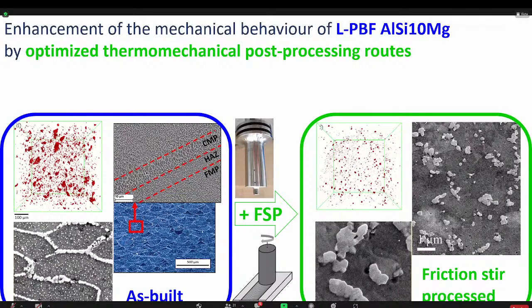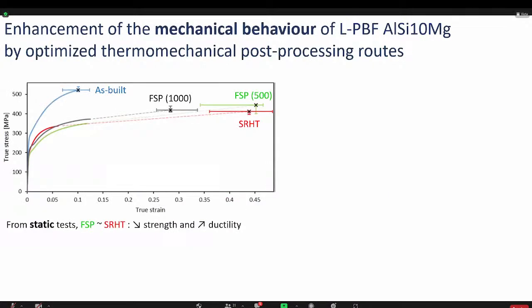In terms of mechanical properties, here you can see the static mechanical properties. If you compare, the FSP material is the green one, and the as-built is the blue one. We also compare it with some stress relief material for the red curves. You can see that the FSP material and the stress relief material have quite similar behavior from a static point of view, with a decrease of the strength and an increase of the ductility in comparison to the as-built material.